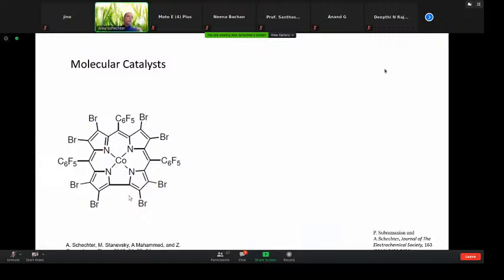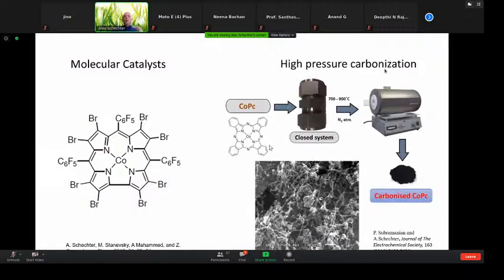That leads us to just a few examples of what we've been doing using this approach. We're developing, first of all, carbon-based catalysts, molecular catalysts based on corrole. That was published long ago, but is still a highly cited paper showing a molecular catalyst that is stable in acid solution and can reduce oxygen efficiently. We're able to take a similar molecule and create a very interesting, highly loaded catalyst with a lot of nitrogen in it, and measure the basic properties of this by using a high pressure method that we've developed alongside Professor Ariel from Ariel University.